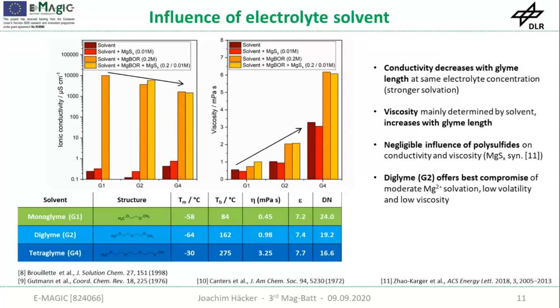And based on these insights, diglyme offers the best compromise, as Piotr already mentioned before. It offers a moderate magnesium solvation, so the desolvation energy is lower compared to tetraglyme. The volatility is lower due to the higher boiling point, and the viscosity is still quite low. But still, also with diglyme, we observe this polysulfide shuttle and the self-discharge. So it's not perfect, but from this glyme family, I would recommend to use this one.